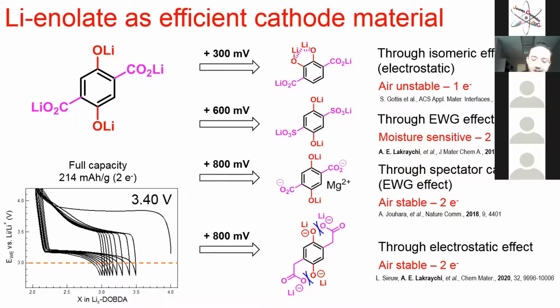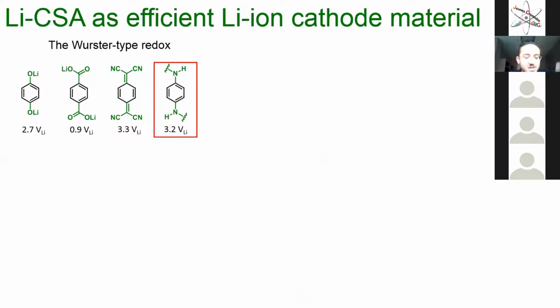And the way to do that, you just need to look at the molecules. On the left is the one that I just showed you, and as you can see, this one is showing 2.7 volt. Those belong to what we call the Wurster-type redox system. It's based on an aromatic. If you change what we call the ending group, here you have a carboxylate, so the potential will drop to 0.9. If you change it with the cyanide group, this will go to 3.3. So depending on the chemical nature of the ending group, the potential will be up or low.